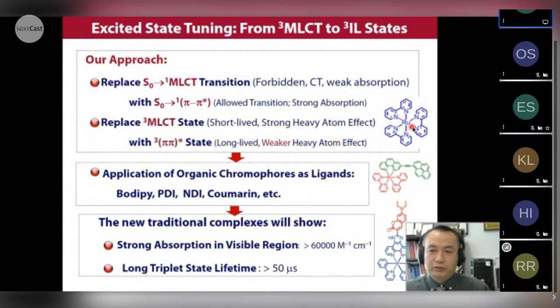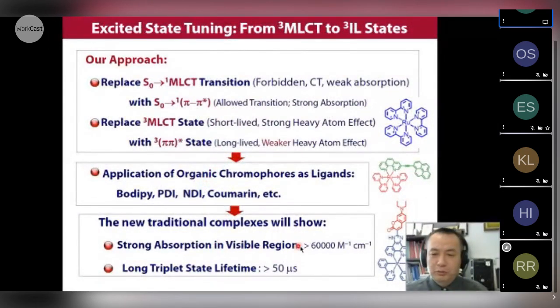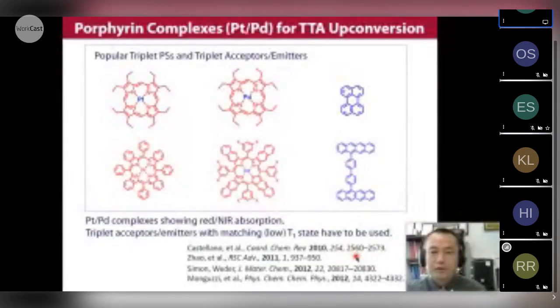The reason for the short triplet lifetime of ruthenium complex is because there is a very large spin-orbit coupling for the MLCT triplet state. That strong coupling will reduce the triplet lifetime. So by using organic chromophore as a ligand, the chromophore should be with proper energy level compared to the MLCT state. Then we will have a strong absorption of visible light, and we will also have much longer triplet lifetime. That will improve the property of our triplet photosensitizer.